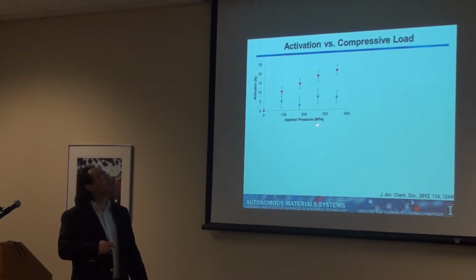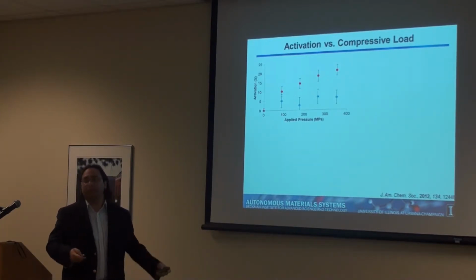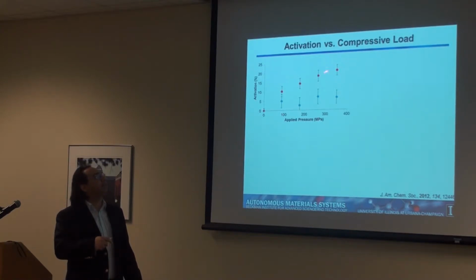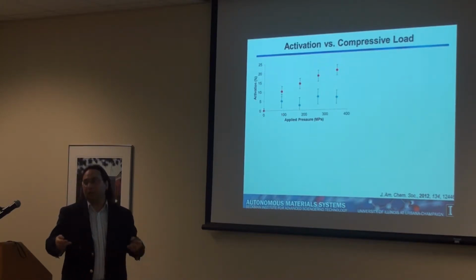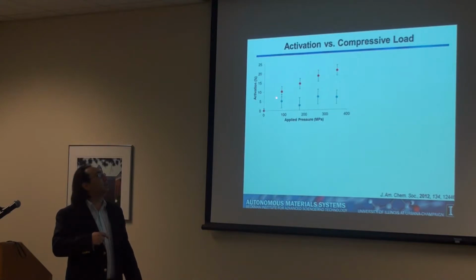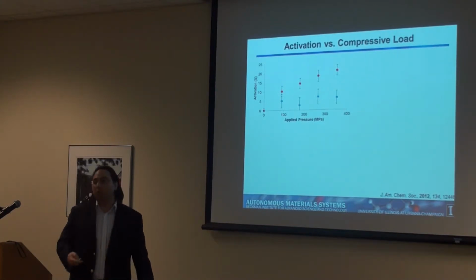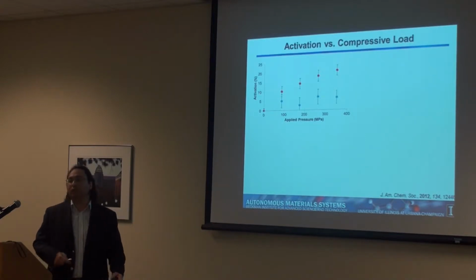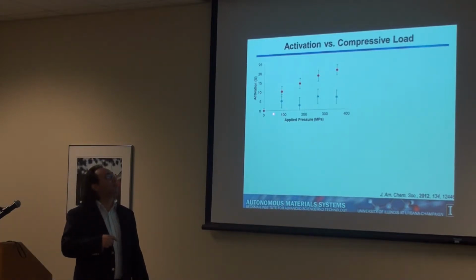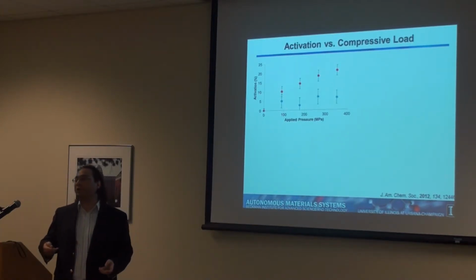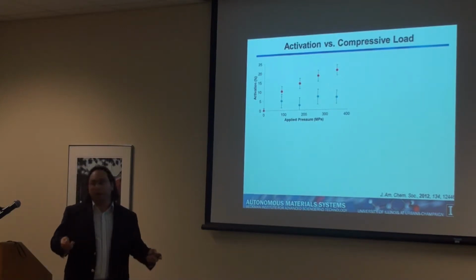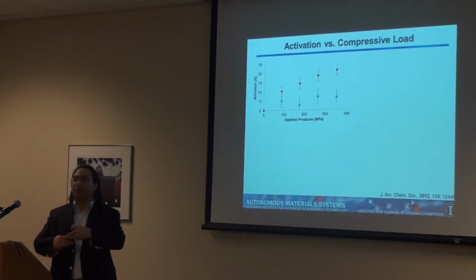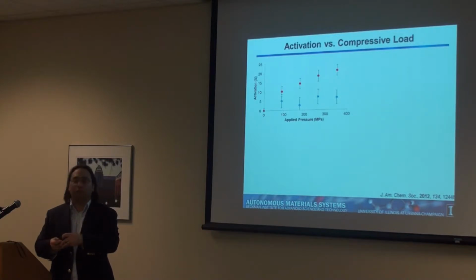So applying different pressures, different mechanical force, in the case of my system, the activation goes up. In the control case, there is some small activation, around 5%. It's probably thermal, but it's unrelated to how much mechanical force I'm applying. Now, I demonstrated that I'm losing that molecule that I incorporated.